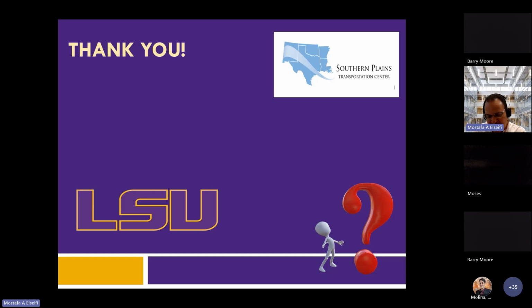And again, some states tend to use a lot of OGFC. Here in Louisiana, you feel like the interest went up and now it's going down again. So again, the DOT always wants to optimize their funds. And if they know that OGFC will last for 3 to 5 years, they will probably not use it. And that's a challenge that we have. So even though the functional benefits are tremendous and in my opinion are really good, this is something that we need to address so we don't fix a problem and end up with another. And that's where we are currently with this type of mixes.